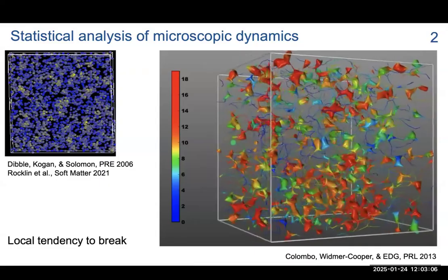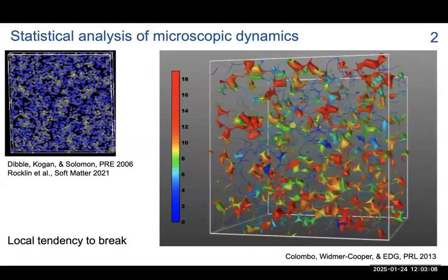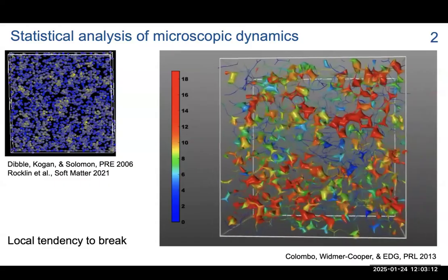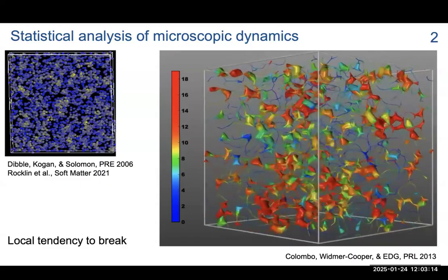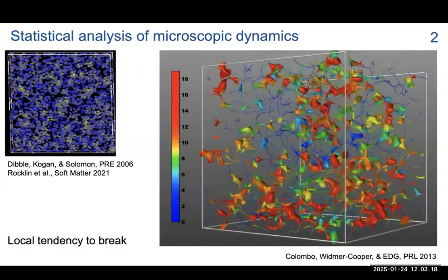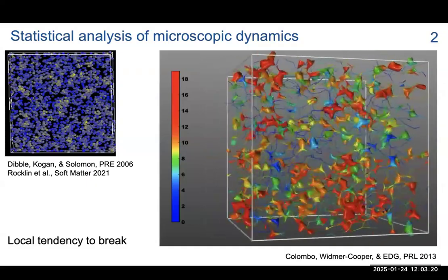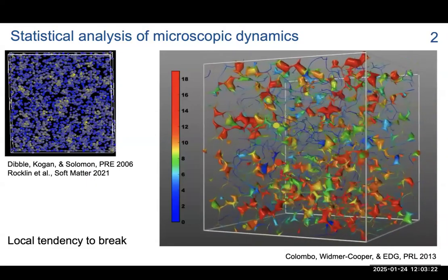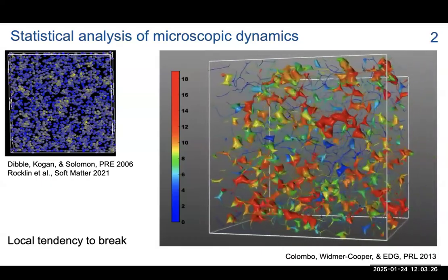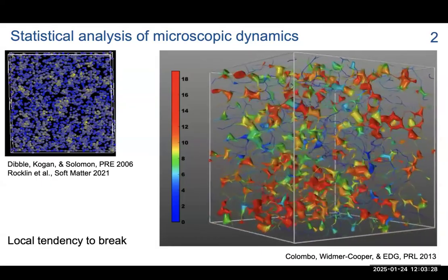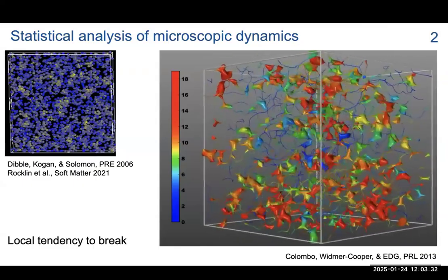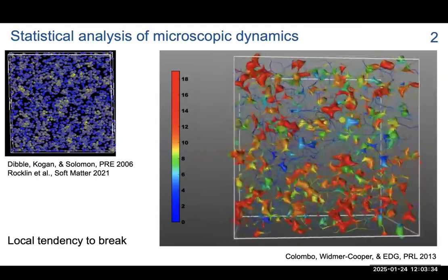But I want to emphasize that this is not, and that's what made this analysis very hard, and now it all makes sense in the things that we're doing. It really depends on the network topology and not the local coordination. So just looking at what one particle does locally, or even on average over the network, is not enough. You really need to identify larger scale motifs that form the topology of the network in order to understand how this works out.